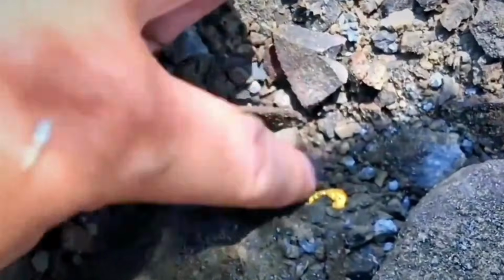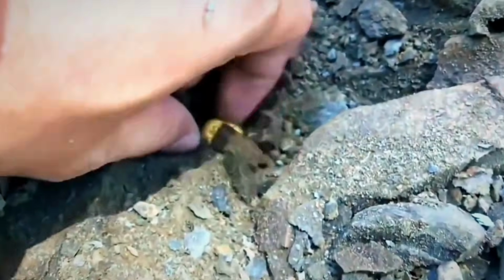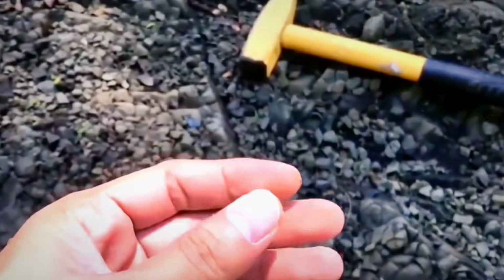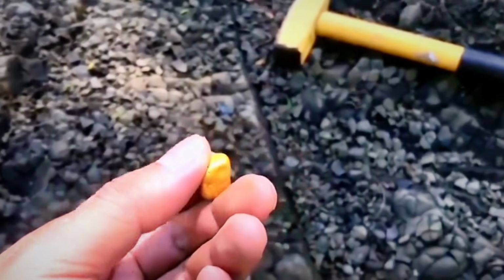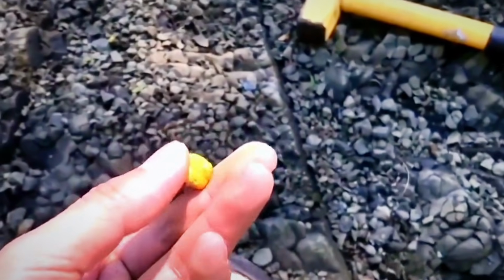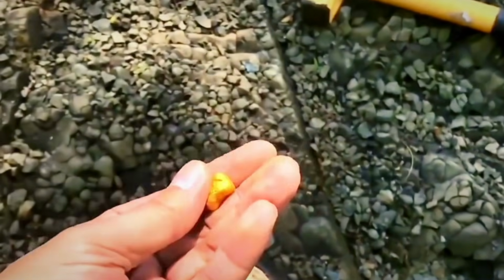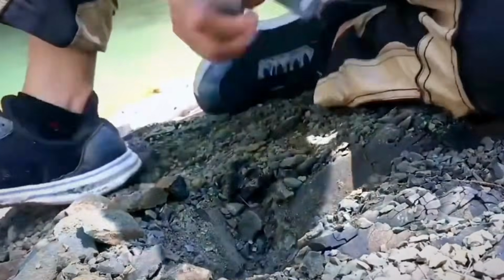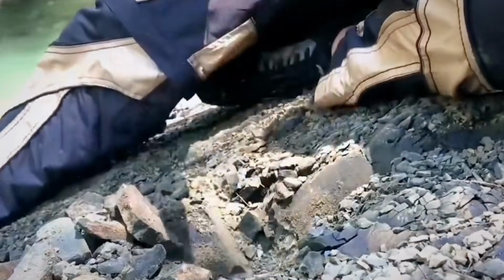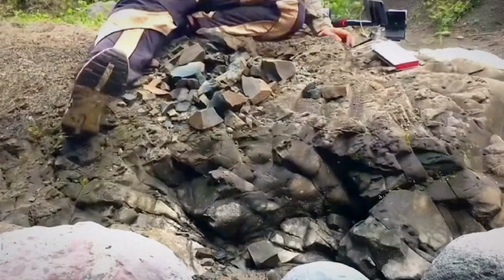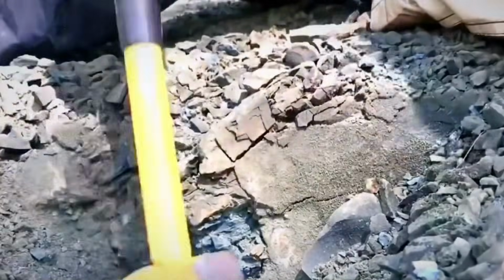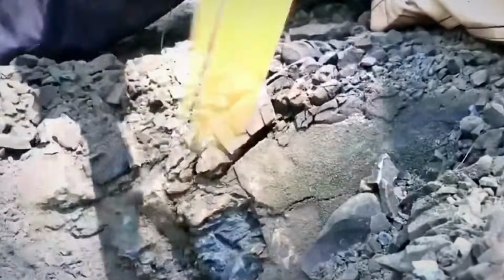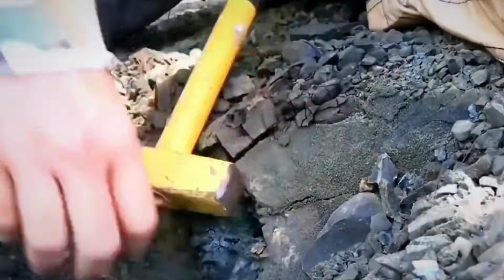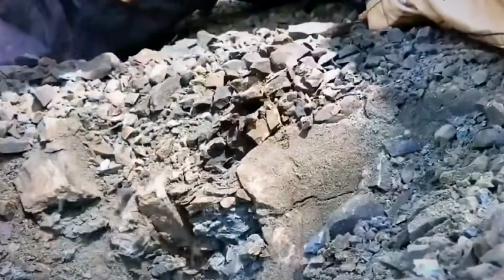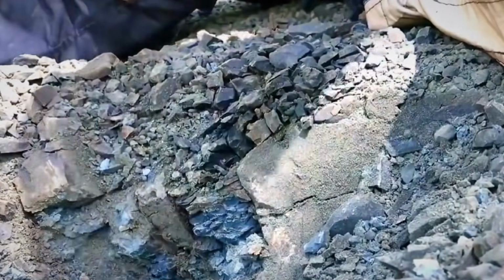Next comes the secondary crusher, often a roll mill or hammer mill, which crushes the jaw output down to sand-sized grains or finer. This is where early liberation starts. In some cases, free milling gold will begin to appear, tiny particles flaking out from the crushed host, ready for gravity concentration. But unless the ore is unusually rich or soft, this still isn't enough. Many gold particles are microns in size, far smaller than sand grains, and remain locked inside sulfide lattices or microfractures. That's where pulverization enters. Using a disc pulverizer or ball mill, the material is reduced to a fine flour-like powder.